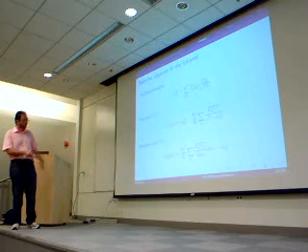The imaginary part is given in this way, which is similar, so that we have a spectrum which is localized. We consider here an infinite lifetime, so delta is infinitely small, and the spectrum has peaks corresponding to excitation at the same frequency as the vibrational modes.